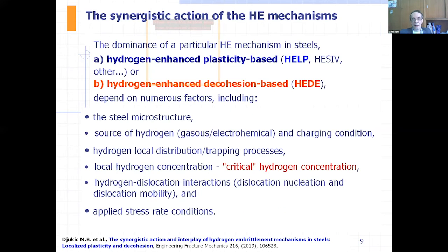So we could summarize that the dominance of a particular one of these 2 mostly accepted mechanisms depends on numerous factors. I will just list them. We have numerous influencing factors like steel microstructure, source of hydrogen, hydrogen local distribution and trapping processes. Also the local hydrogen concentration and distribution, and reaching of the critical hydrogen concentration. Very complex phenomena related to hydrogen-dislocation interactions. And of course, finally, the applied stress rate conditions define which of these two mechanisms will be dominant in a particular case, and also the change between these two mechanisms.